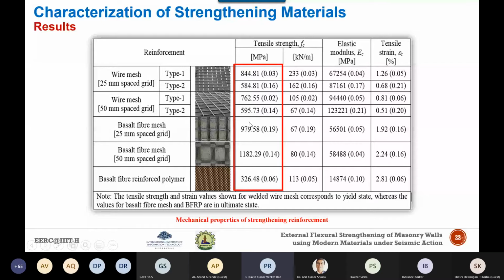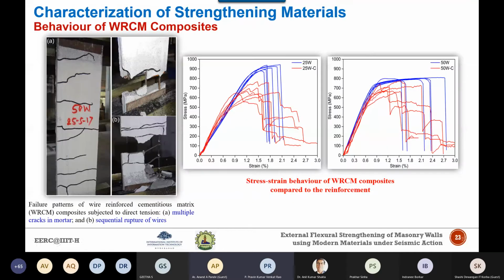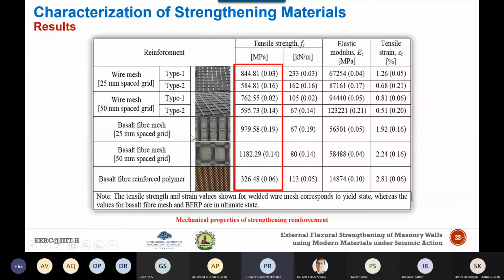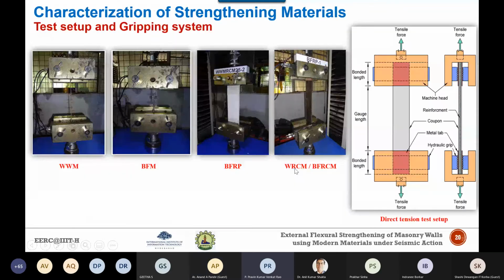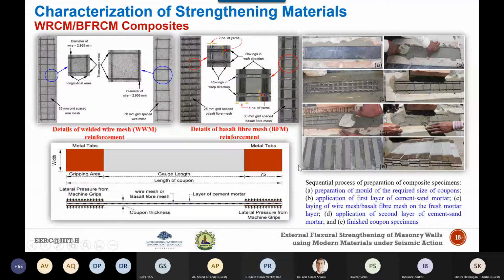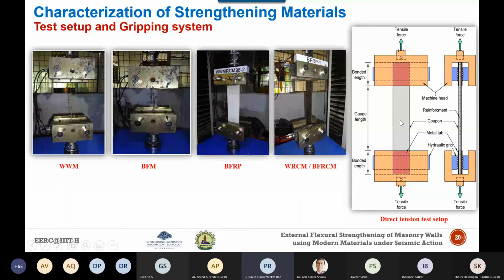In the case of WRCM, representing the wire reinforced cementitious matrix, what is the WRCM composite? This is the specimen where a wire mesh has been inserted between two layers of cement sand mortar plaster. Here you can see that the cracks have occurred along the width and have been distributed evenly over the full length of the specimen.